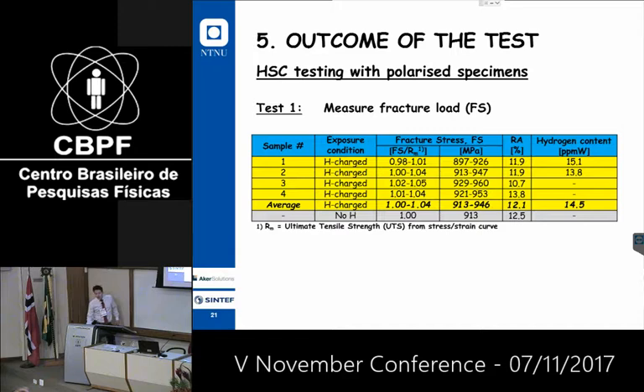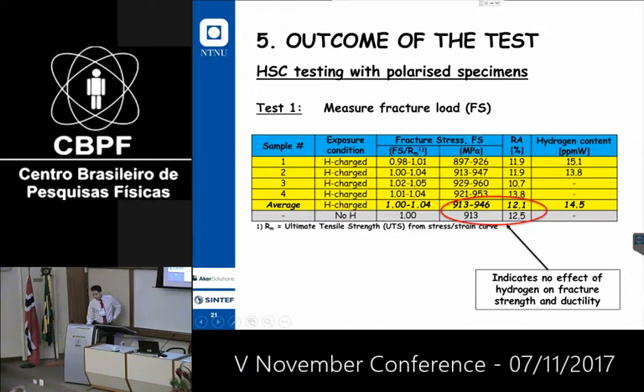But what did the hydrogen embrittlement testing indicate? We see that we have in the charged samples about 14 ppm weight hydrogen content. You saw that before, Ann-Karin, she was burning it off from the samples. But without any charging, we have about the same. So there is no indication that hydrogen influenced the fracture, the strength and ductility.